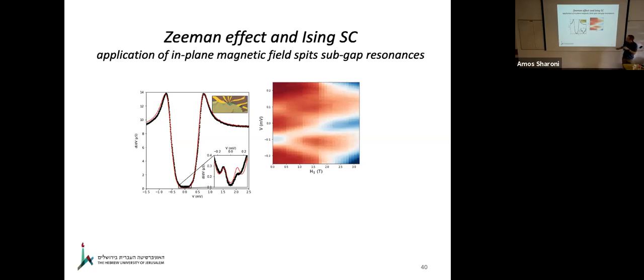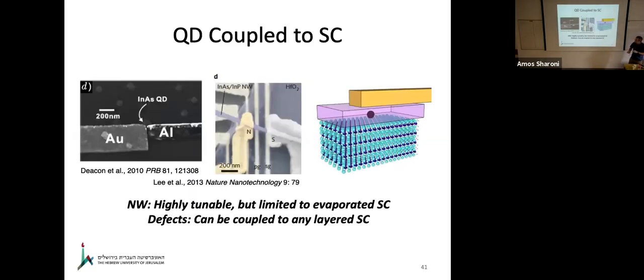The reason we know that this is a defect is that it's almost a textbook reproduction of what you expect from a quantum dot coupled to a superconductor. Quantum dots coupled to superconductors have been studied quite extensively using nanowires. You have a nanowire and you can deposit an evaporated superconductor such as aluminum or niobium or vanadium. You can create dots and barriers.